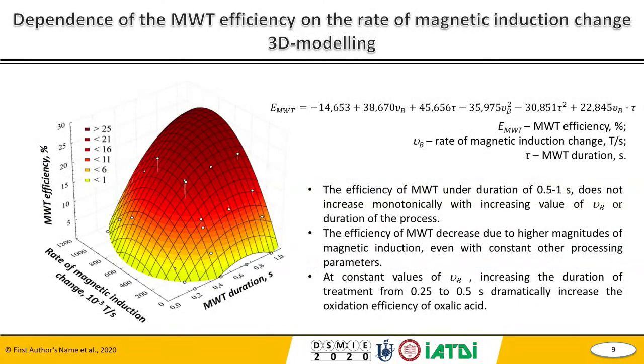Statistical processing of experimental results allowed approximation of the regression equation of magnetic water treatment efficiency on the rate of magnetic induction change and duration of process that you can see on the slide. The efficiency of magnetic water treatment under duration from 0.5 to 1 second does not increase monotonically with increasing value of magnetic induction change, and reaches its maximum in the range from 0.4 to 0.8 Tesla per second.